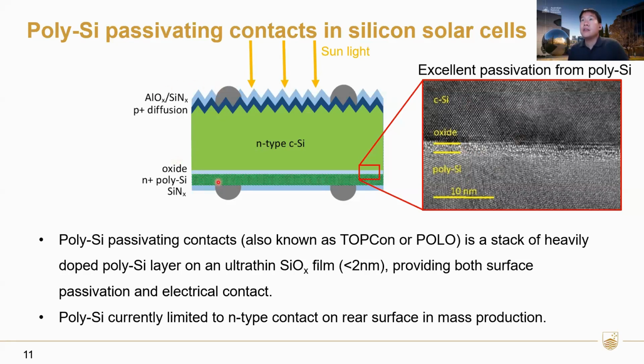So the figure on the left here shows a typical cell structure of the so-called TOPCon cell. This is the dominant, or will be the dominant, cell structure in the next 10 years. Essentially, it's an N-type silicon wafer with a boron diffusion on the front. And the rear surface is where we apply the TOPCon layer, so the oxide and then the N+ polysilicon layer. The polysilicon layer is amazing. It's one of the lowest recombination sites right now within the cell, but unfortunately, it is still limited to the rear surface due to the unintended parasitic absorption of the polysilicon if you place it on the front surface.